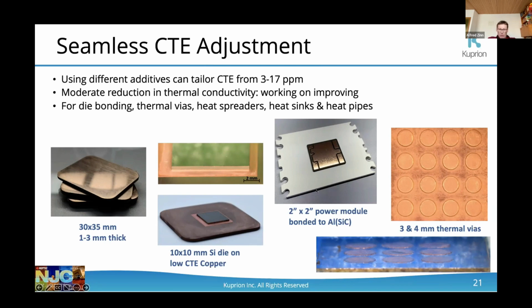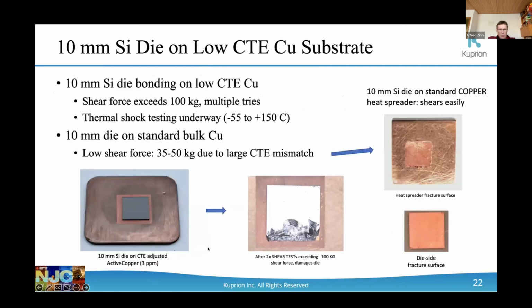This is another really cool implementation where we were able to directly bond to a large AlSiC, aluminum silicon carbide, heat sink or heat spreader plate, and put this AMB silicon nitride substrate basically bonded directly to it. So very cool stuff. Here's a little more information on the 10 by 10 that we put on this plate. We've done already several thousand thermal shock cycles on this, and it just doesn't budge.